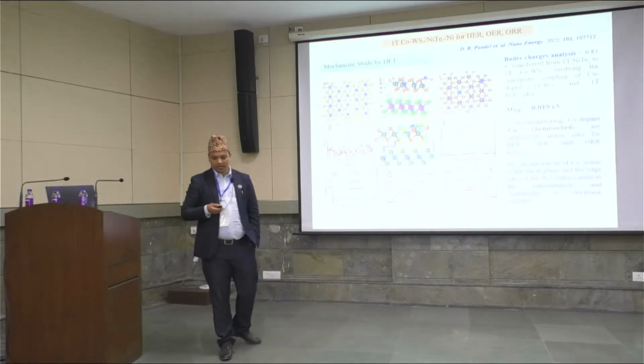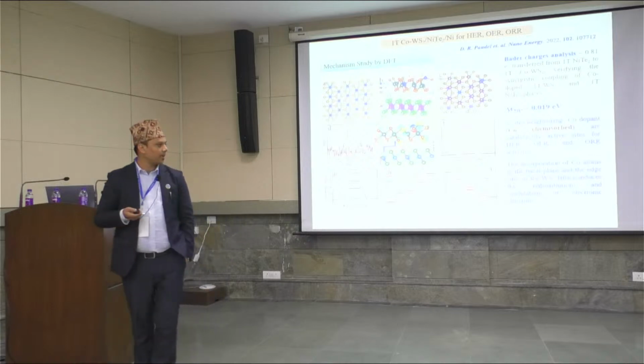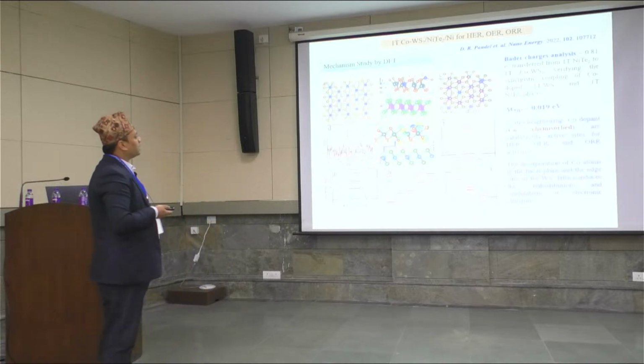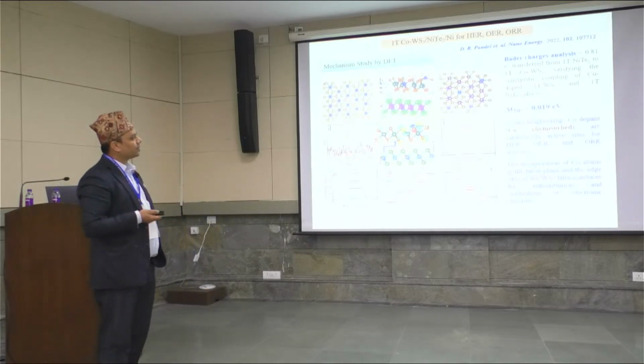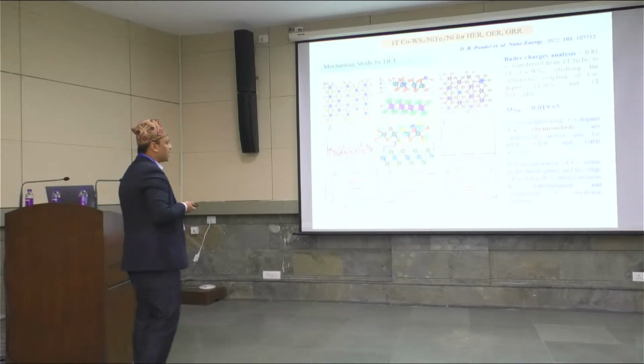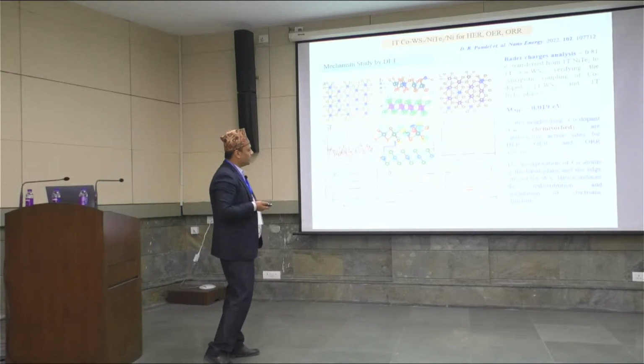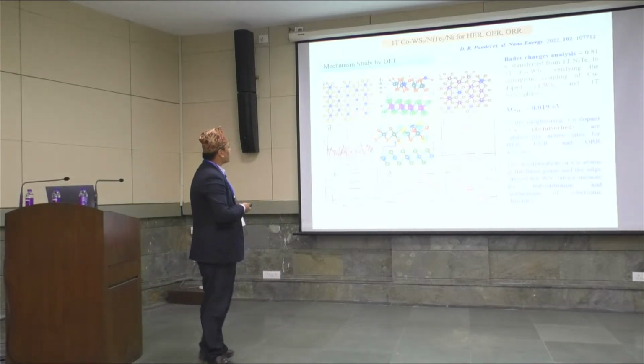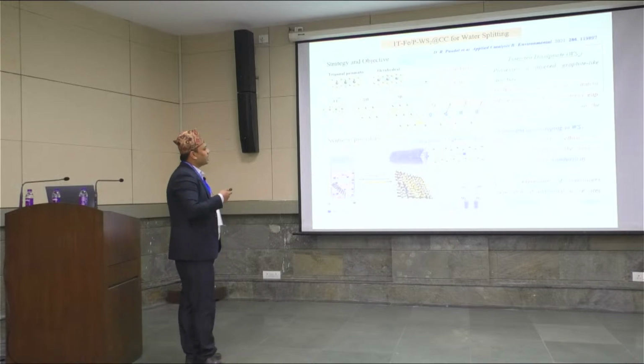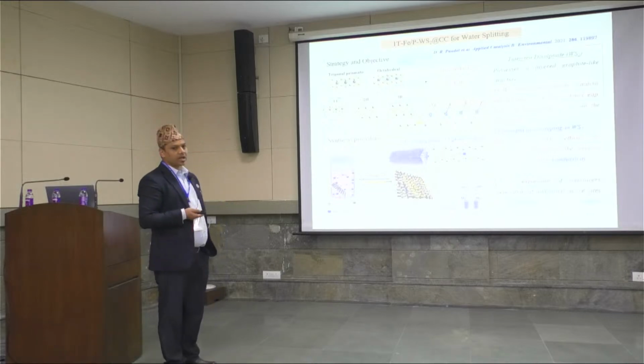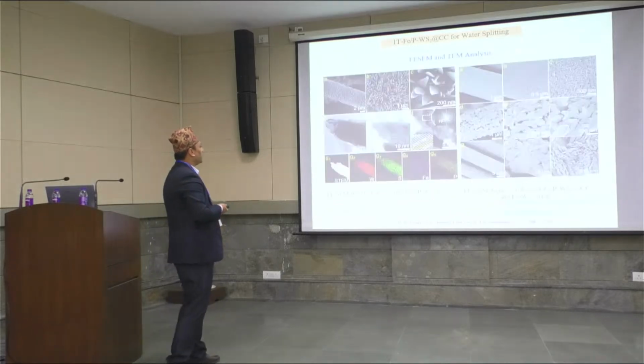This work was done by our collaborator from Japan, Osaka University. And he calculated the Bader charge analysis around 0.81, and the free energy calculation is around 0.01 electron volt, which is very good catalytic behavior. And this one is also published in Applied Catalysis B: Environmental in the 2021 issue.